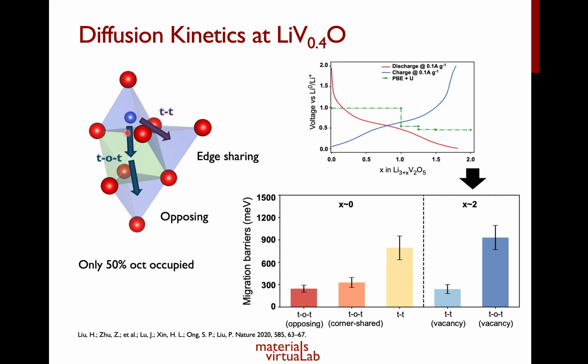So we hop from our tetrahedral to the intermediate octahedral, then to another tetrahedral site. Now, to our surprise, at Li5V2O5, the direct tetrahedral to tetrahedral hop is actually much lower in barrier than our tetrahedral-octahedral-tetrahedral hopping process. This is really because we now only have half-occupied octahedrals, and that actually lowers the barrier for this tetrahedral to tetrahedral hop significantly.